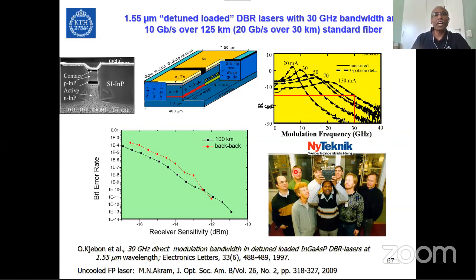And we need fast enough lasers to transfer data. And so at the time, this is from 97, we demonstrated 30 gigahertz bandwidth. So this is the buried heterostructure laser. You have the laser structure and you are burying the laser structure in the semi-insulating indium phosphide here.